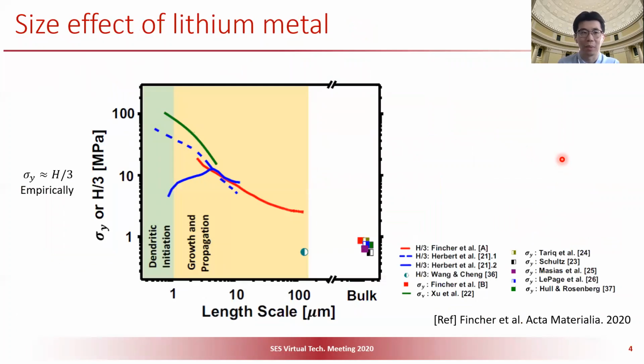Why is this so important? Because according to our existing knowledge, there is a very strong size effect in lithium metal, particularly in mechanical behaviors. For example, this plot is made by Professor Fincher in his recent publication. So we can clearly see that there are a lot of studies already, right? The x-axis is length scale and the y-axis is yield stress. So there are many publications that tested the bulk strengths, and also there are a lot of publications focused on the length at a nano and micro scale.